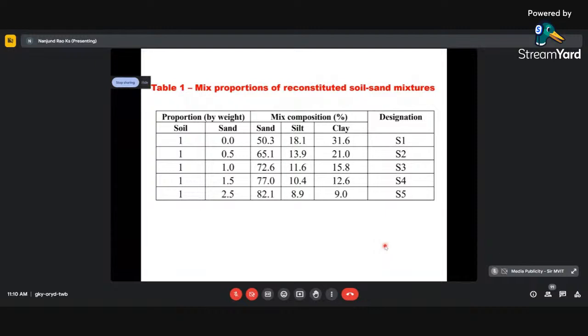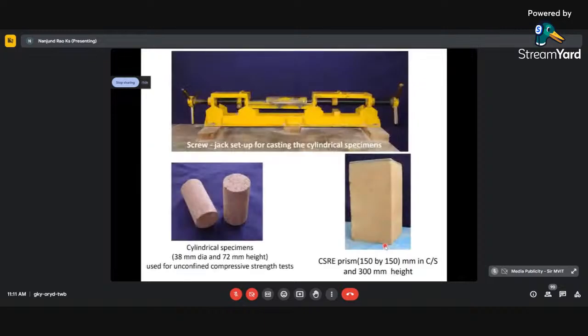Yeah. So S1 is not reconstituted. The soil had about 0% sand added, 50.3% what was there earlier itself in it. We didn't add anything extra, 18.1% silt and 31.6% clay. Then, in order to bring down the clay of 31.6% to lower levels, in S2 we added sand over and above the sand which was there in the silt and sand, so that it is brought down to 21% clay. Like this, we brought it down. S5 is 9% clay only, but we added 2.5 sand to the soil. And that is how we ended up with 9%, 12%, and 15.8%. That is S3, S4, S5, which are called reconstituted soils for rammed earth construction.